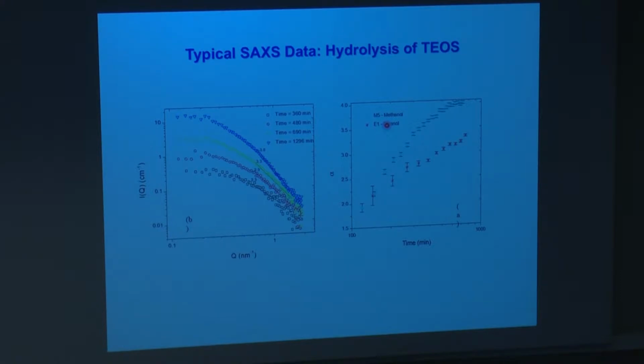So using small angle X-ray scattering to look at the particle growth as well as looking at the slope of the scattering curve, it tells you something about whether or not the particle is kind of a fluffy type of object that doesn't have extremely high density, to where it goes all the way up to 4 in the case of methanol. And at that particular point, you have a spherical particle that has a smooth surface and where it's a solid. So these were some of the things we were able to get from the small angle scattering.